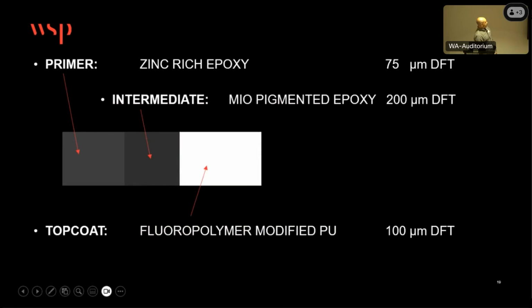And this is schematically what it would look like. Not a lot different from your average 3-coat paint system, where you would have a really good surface preparation, a zinc-rich prime coat, a barrier coat pigmented with micaceous iron oxide to provide that longevity, and then a fluoropolymer top coat.